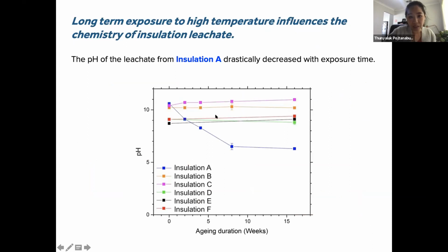So we can see that all of the insulation didn't change much in terms of the pH, but insulation A had a significant drop in the pH with the aging time. If we take just the fresh insulation at the aging time of 0, all of the insulation would meet the criteria provided by the EFC that the pH should be between 7 to 10.5. But as you can see, particularly in insulation A, the pH dropped significantly. After 8 weeks, the pH came down to about 6.5 and stayed steady around 6 to 6.5. So this suggested that during the thermal exposure of insulation A, there is some change in the chemical composition, either the degradation of the additive that leads to the leaching of the acidic chemicals.